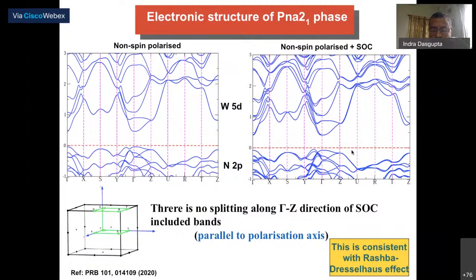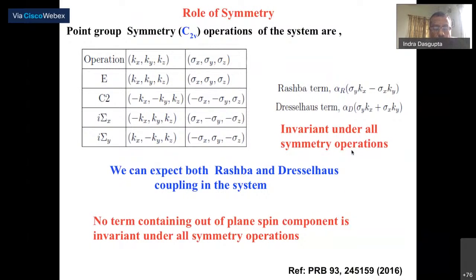This is because your electric field is along the Z direction, and as a consequence, the magnetic field which is going to get generated because of this in the rest frame of the electron is going to live in the XY plane, so it cannot split anything along the kz direction. This is a good observation because it tells us that the spin splitting is essentially of the Rashba kind. You can also look at the point group symmetry and find out that both the Rashba Hamiltonian as well as the Dresselhaus Hamiltonian are invariant under this point group symmetry. So in principle, we expect the presence of both the Rashba effect and the Dresselhaus effect. And of course, if they are in equal proportion, then we also expect the existence of persistent spin texture. Let's see what the story is as we do some more calculations.